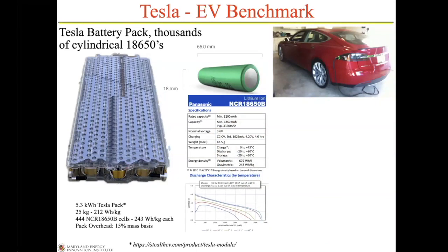And why is that? Well, in fact, it's very important that you maintain the temperature of these cells. And so they have to have a cooling system in it to maintain the operating temperature. If it gets too low with the current liquid electrolytes, you have a significant energy or power loss. You can see that in the plot there from the manufacturer's battery data. You can also see that there's a big ohmic loss at zero degrees, because liquid electrolytes will tend to freeze and reduce conductivity at lower temperature. And so you have a much lower energy that you can get and much lower power you can get out of these cells. And so they have to maintain a high enough operating temperature so that doesn't happen.